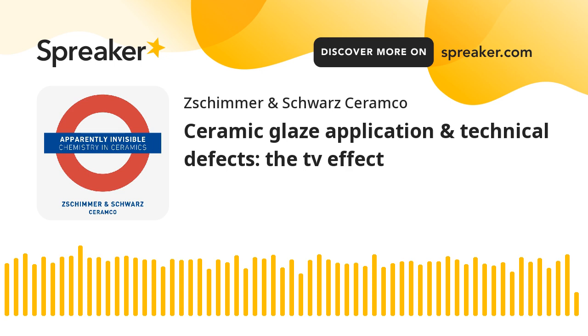Among the most popular, we can mention the orange peel effect, and to be honest, I'm not sure if this English translation makes sense, but it's an effect deriving from an improper leveling of the glaze, just to put it simple. We can also mention dusting phenomena promoted by a lack of cohesion within the system, holes and pinholes deriving from an improper drying time or from a chemical incompatibility between the layers that form the ceramic body, such as engobe, glaze, etc. But, and here we come to the subject of today's episode.